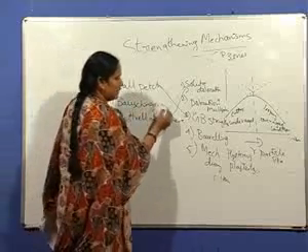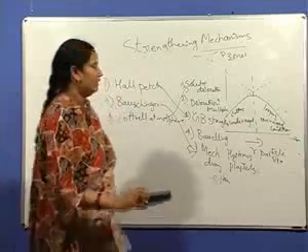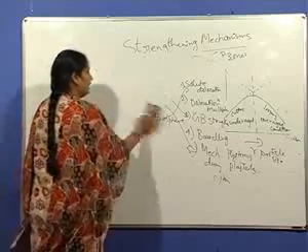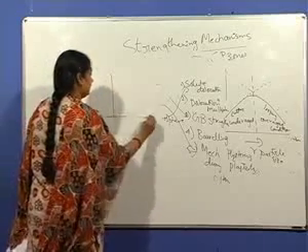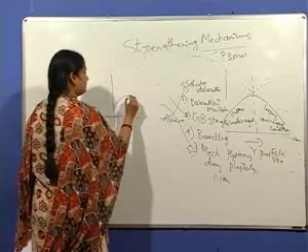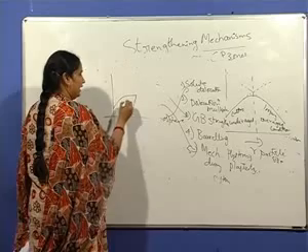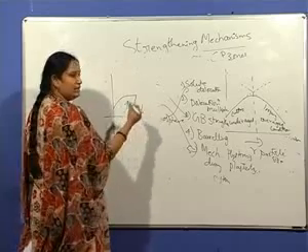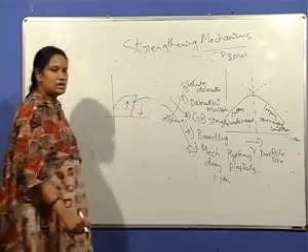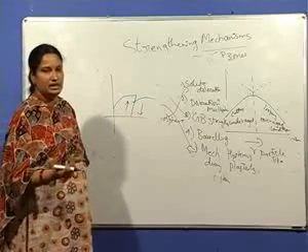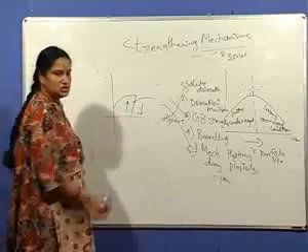Bauschinger effect is mechanical hysteresis during plasticity, because for the Bauschinger effect, I have drawn the figure. When a material is loaded in one direction, if it is loaded in tension, yielding occurs. Beyond yielding, if you unload that material and again reload that material in the opposite direction, the yield stress is lowered. This lowering of yield stress when a material is loaded in one direction followed by another direction is the Bauschinger effect.